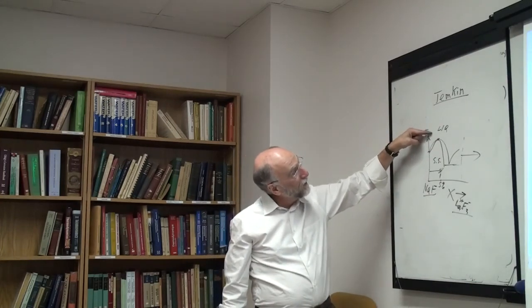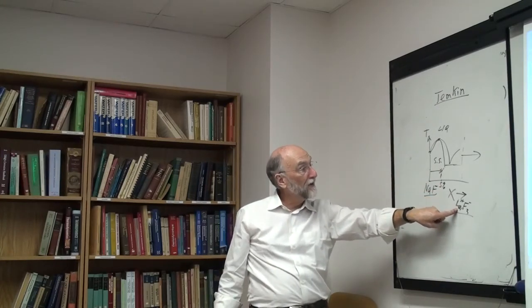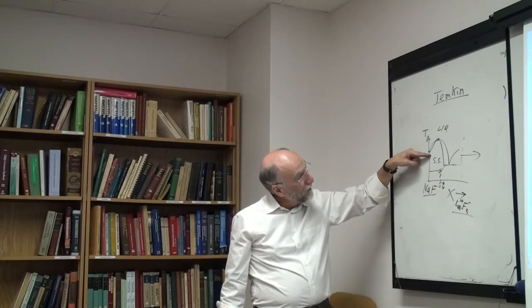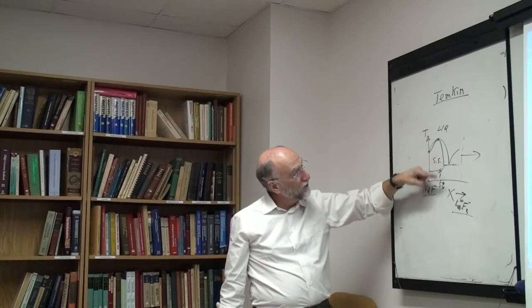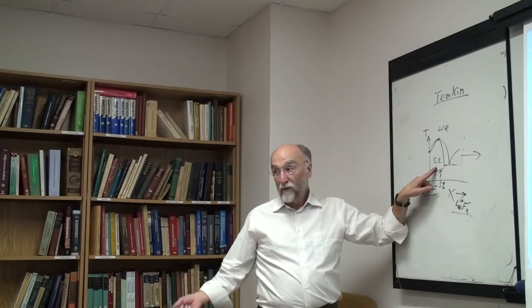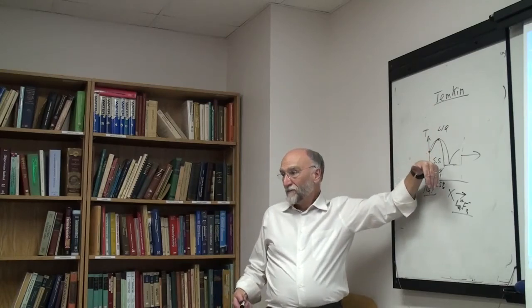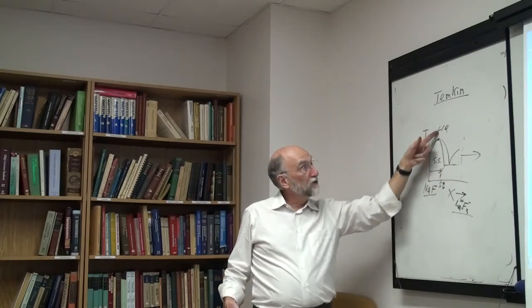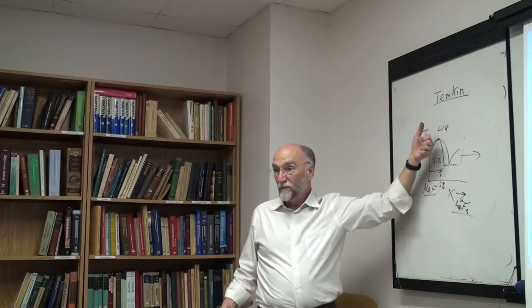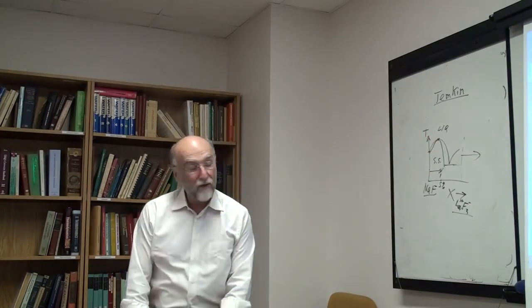As I'm adding to the liquid, I'm only adding one foreign entity, one foreign particle, lanthanum, which mixes. As I'm forming the solid solution, at least in dilute solution, I'm forming a lanthanum and two vacancies, so I'm getting three times the entropy. Okay, so the solid solution is stabilized because of this additional entropy, which gives you a maximum. It's stabilized relative to the liquid, pushes it up. It's not enthalpy, it's entropy, an entropic stabilization.